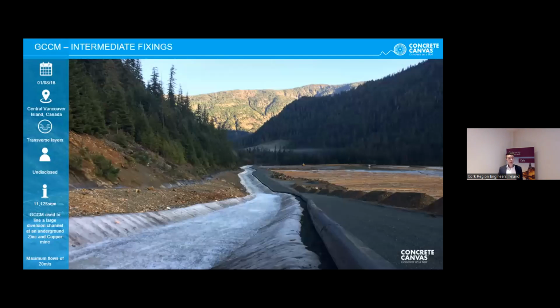There also might be a requirement for intermediate fixings, depending if there's high hydraulic shear loads within a channel. This is a project that I worked on 8 or 9 years ago now in Canada, at Myra Falls, where they used earth percussion anchors at 1 meter intervals because of the high shear loads within the channel. This project was designed to handle flow velocities in excess of 20 meters per second. So intermediate fixings are typically only required when you have high shear loads within the channel itself.